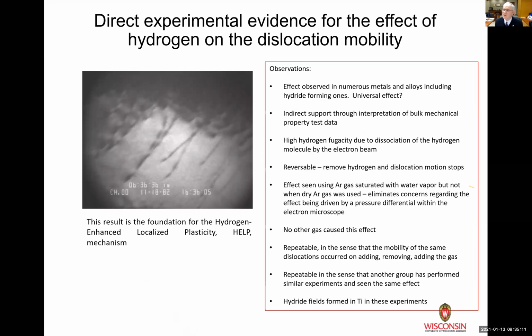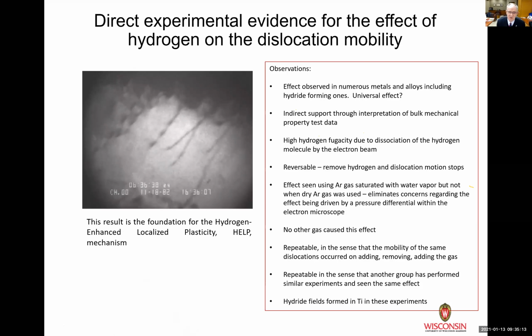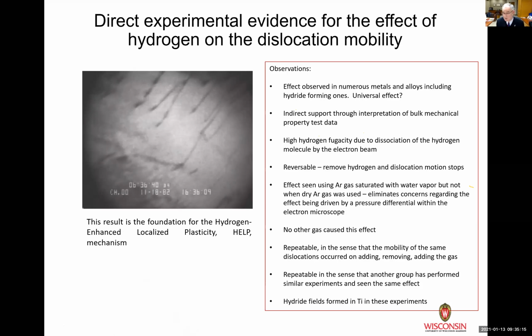We could take the hydrogen back out, and the dislocations will stop, which they should, because the hydrogen embrittlement effect is in fact reversible, right? You take the hydrogen out of the material, you're going to go back to the old behavior and the old failure. You put the hydrogen back in, it should go back to the hydrogen embrittlement. We were able to show that by adding hydrogen into the microscope, taking hydrogen out, putting it back in. The dislocations would always start moving.